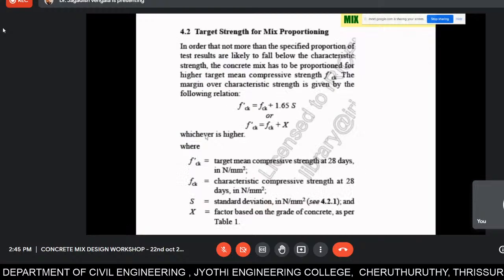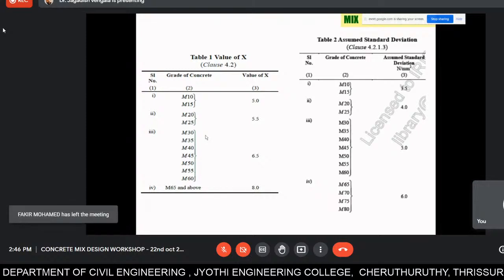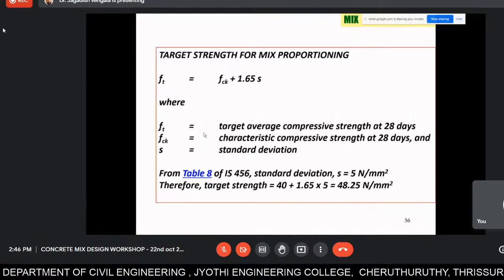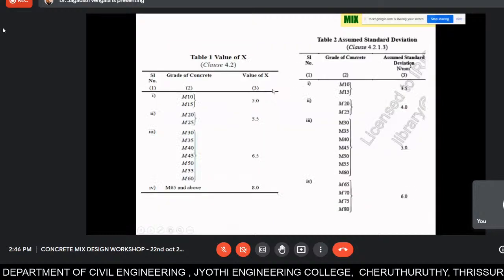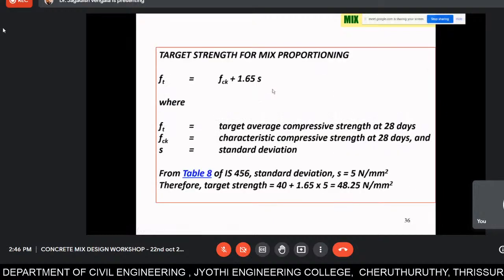So if it is M40 grade of concrete, it is 40 plus 6.5 in case of X, or otherwise 40 plus 1.65 times the standard deviation. That's what I have given here. So f_ck plus 1.65 times the standard deviation. Our standard deviation for M40 grade of concrete is 5. So 40 plus 1.65 times 5, that is 48.25, is your target strength. You have to design the concrete for 48.25 MPa.